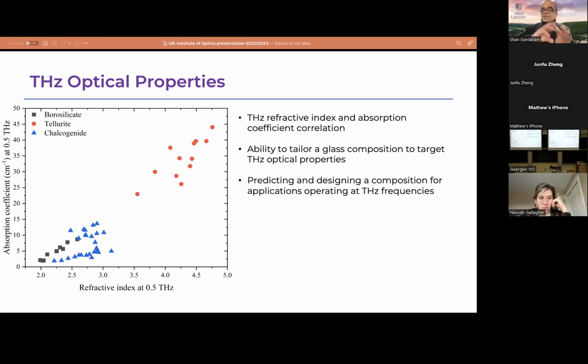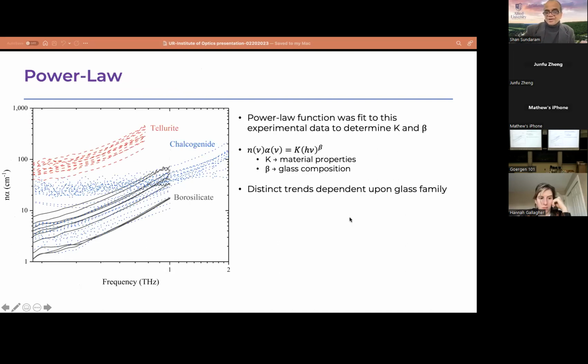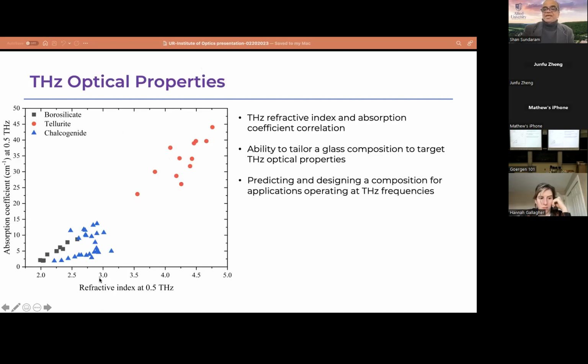But this one shows some clumping of the data, but the thing it brings out to you is we at least have two distinct families, this overlapping family to focus on. So now you can use this data set to decide if you want high absorption and a high refractive index, or low absorption and low refractive index, what composition I should be really using for my glass. So depending on whatever your optical application may be, the absorption level and the loss and the refractive index, then you can go to a correlation like this and try to guess which glass I can use and which composition I can tailor to get the property I want.